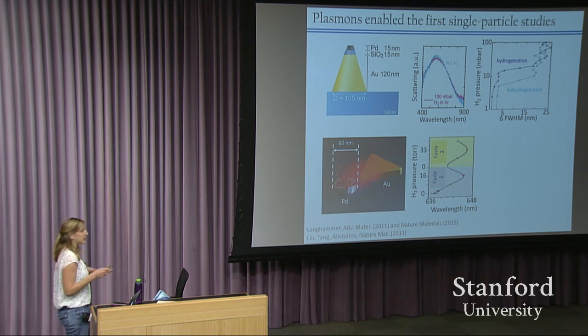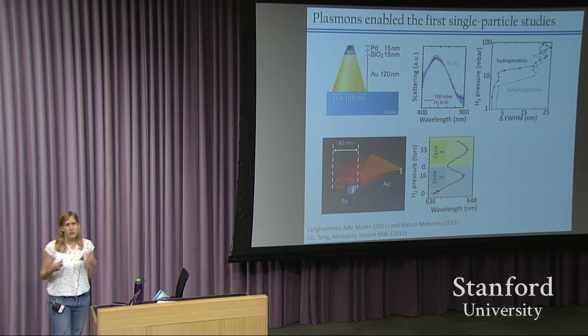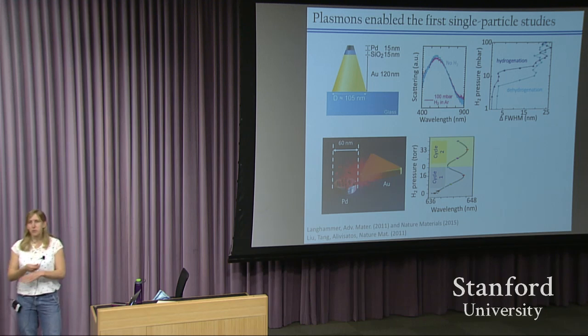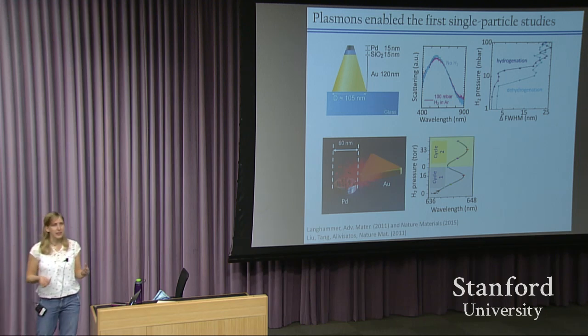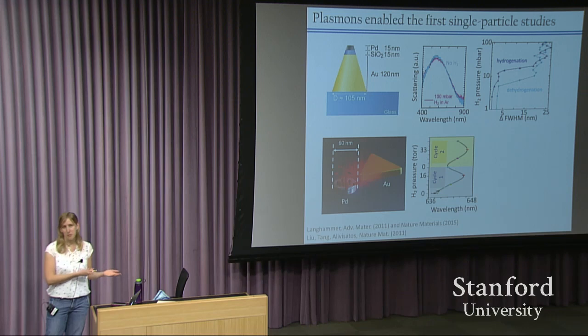Here they were looking at shifts not in the full width half max, but in the peak scattering signal. And they saw isotherms that were a little bit more sloped upon cycling. So these are just a couple of studies, but if you look broadly through the literature, there is a lot of ambiguity as to what might be happening in this particular system as you nanostructure the materials.